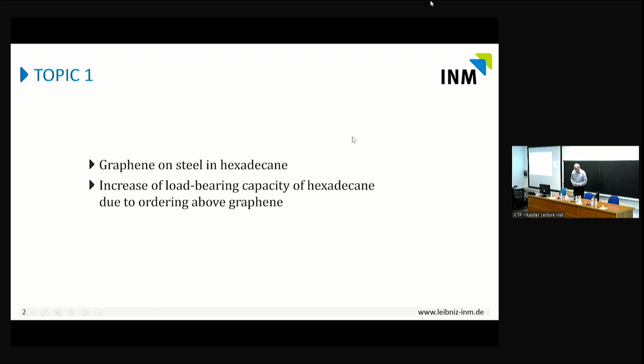So topic number 1 is actually about graphene on steel, real steel. So we polish a steel surface, we put graphene flakes on the steel surface, and we were wondering how this will change the lubrication capabilities of hexadecane as a model alkane lubricant. And what turns out is that graphene helps the lubricant to sort of form a layer that can support load.